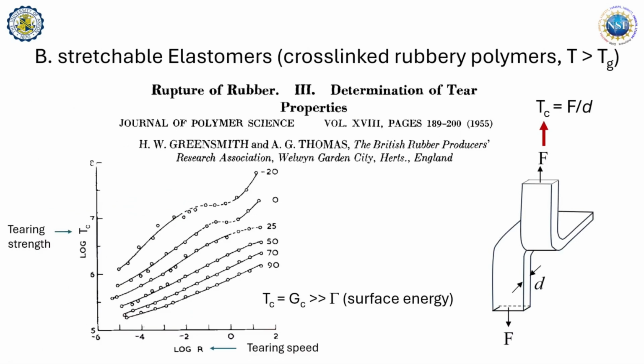So let's review the second problem, elastomeric fracture. This is the bigger part of the picture. In other words, there are more problematic issues about stretchable elastomers. So the first thing that you find exactly 70 years ago, which you can do conveniently by peeling because your rubber is very flexible, so to speak, is that you can peel. You find the faster you peel, the more resistance you find, more force there is. But more amazingly, when you go to lower temperature, same peeling rate, you have to use a lot more force.